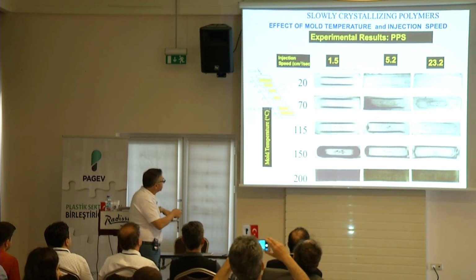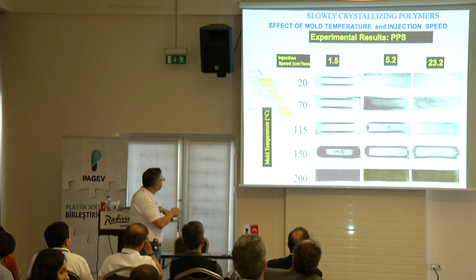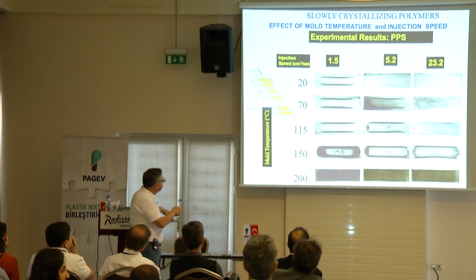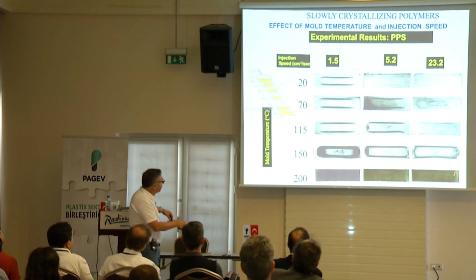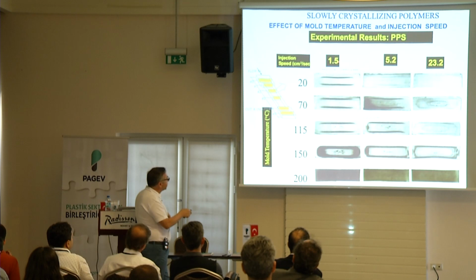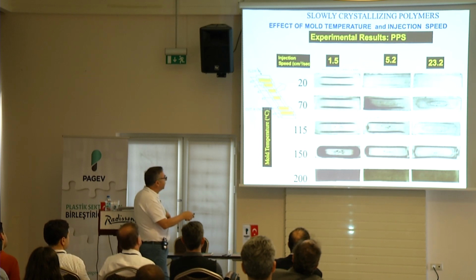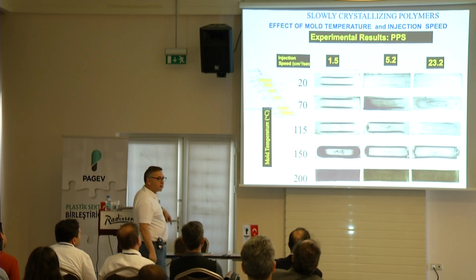This is the effect of mold temperature, same conditions. This is location number 3 on a very simple dog bone shape that was microtomed and laid down in a microscope, so the flow is coming towards you. Skin amorphous, the dark region is crystalline, and core is amorphous. Look what happens when I increase the injection speed. That region disappears.